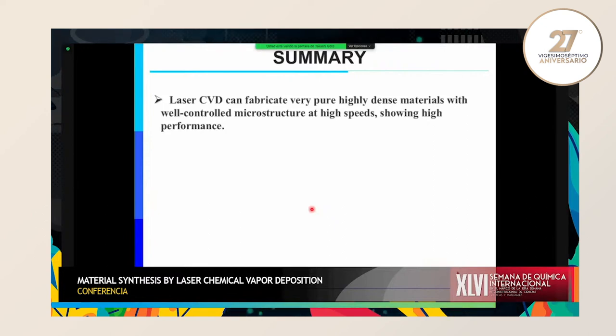That is the reason I say laser is useful, because there is no formation of nanoparticles or nano embryos that cause the film to become a mess. So if you supply very clean, very nice gas to the substrate, that is okay. And almost all materials have self-orientation directions, so the material grows very nicely in some specific orientations. But this is usually very difficult for usual CVD, because fresh gas cannot be supplied to the substrate. That is the point in CVD.